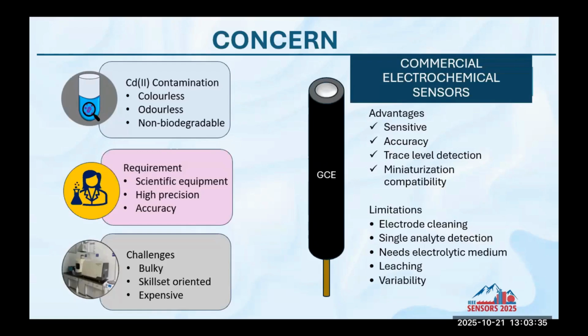However, one great limitation of glassy carbon electrode is that we always need to clean the electrode for the next sensing cycle. And as a result, we cannot modify the electrode permanently. Each time we have to modify the electrode. Mostly we depend on drop casting method to modify the electrode, which leads to leaching during subsequent sensing cycles. Also, it's a lab-based setup, though we can have a miniaturized one, but mostly we are having a lab-based setup.